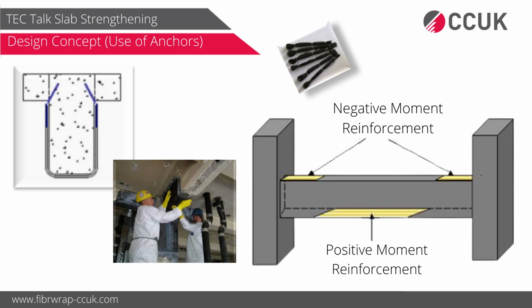That is to improve the sagging moments or positive moments. And it is also applied on top near the supports to improve the hogging moments or negative moments. So again, as we can see, it is only applied onto the tensile faces of the element. Carbon fiber is not recommended to improve the compressive resistance of the element, especially in a section analysis. The reason for that is that carbon fiber is a very low profile material. Like I said, typical thickness of carbon fiber is around 1 millimeter, so it doesn't give you significant improvement in the section modulus. So it doesn't improve the compression significantly. That's why it's generally or mostly applied onto the tensile faces of the element.